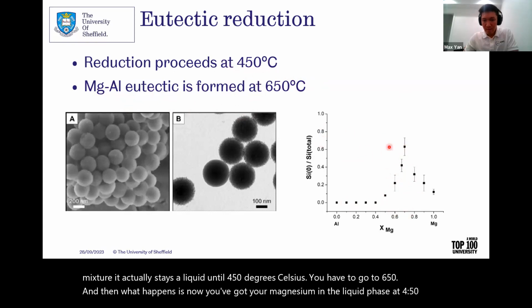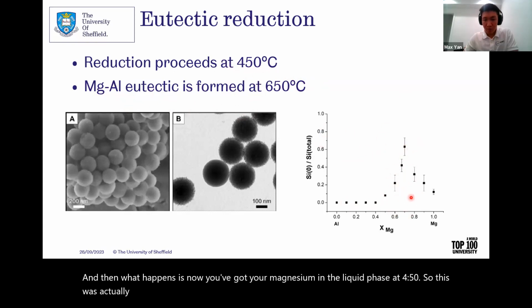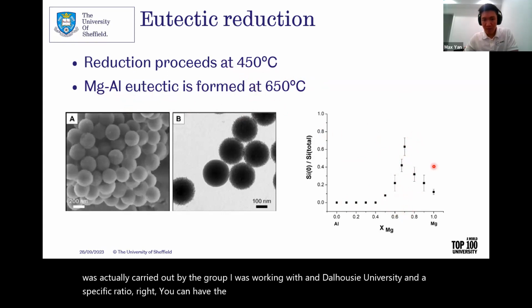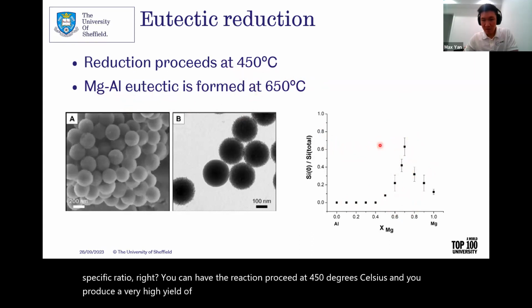So this was actually carried out by the group I was working with in Dalhousie University at a specific ratio, right? You can have the reaction proceed at 450 degrees Celsius and you produce a very high yield of silicon, almost 70%, which is pretty good for 450 degrees Celsius.